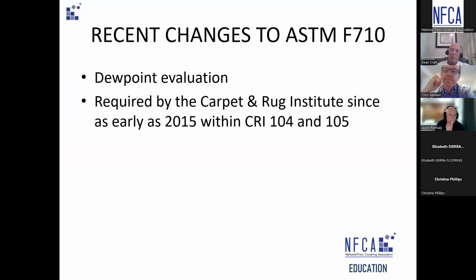But it wasn't until 2022 that dew point became a requirement for the installation of resilient flooring, even though if you look at Carpet and Rug Institute, both CRI 104 and 105, they adopted it back in 2015. The glues changed in 1992. Thirty years later, it became the first requirement to measure the surface temperature of the concrete as a condition and as a correlation with the ambient temp and humidity. And I would offer that at point of installation, beyond your normal clean and prep, dew point, substrate porosity, and appropriate climate are probably your biggest drivers of point of install success.